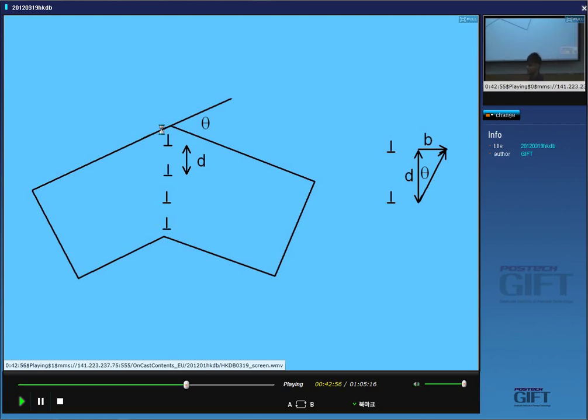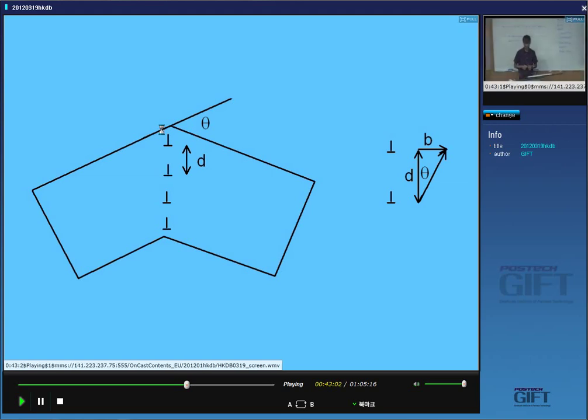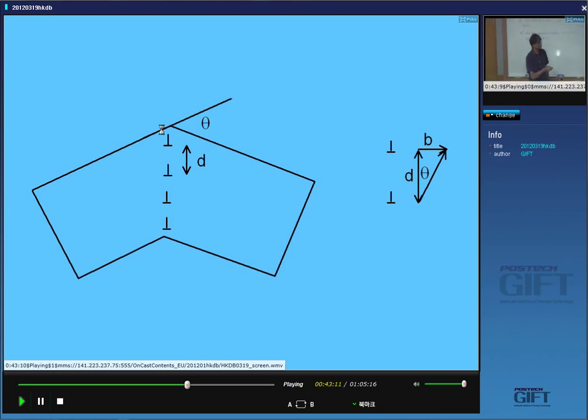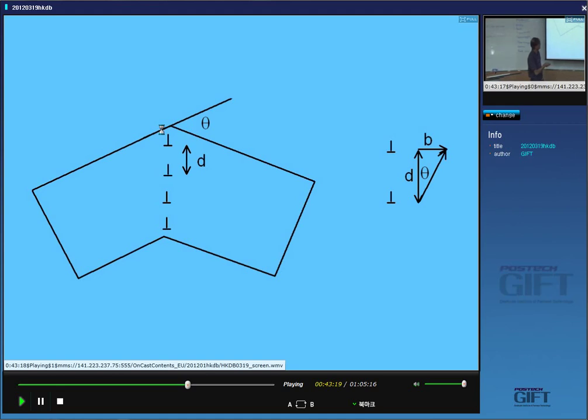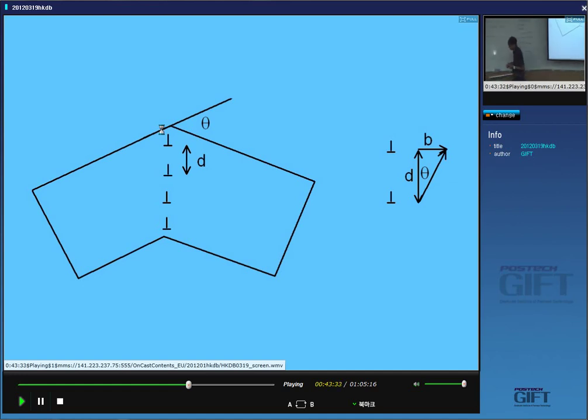This is a particularly simple interface where we just tilted two halves of a crystal. For a more complicated relative orientation, you might need three sets of dislocations with different line vectors to define an interface. But an interface is nothing more than a set of dislocations which allow two crystals to connect. You can see these dislocations in a transmission electron micrograph — I'll bring one in the next lecture.